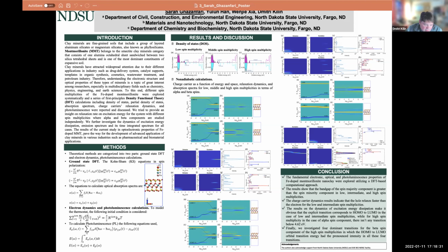But here you're using the diagonal, so you are just looking for the population difference between two orbitals, right? Yes, orbital I and orbital J. And if the higher orbital has more population than the lower orbital, they will emit. There will be a transfer corresponding to emission of light. Stephen, would it make you comfortable if this explanation or formula for it will be there?